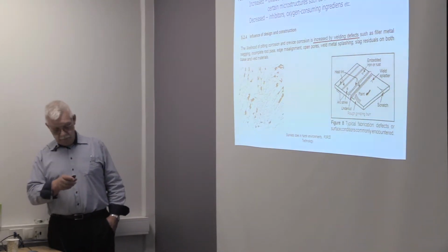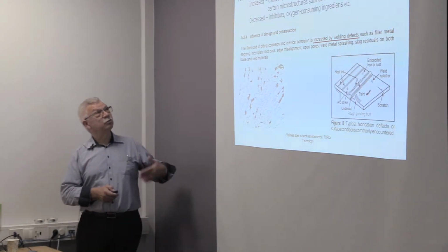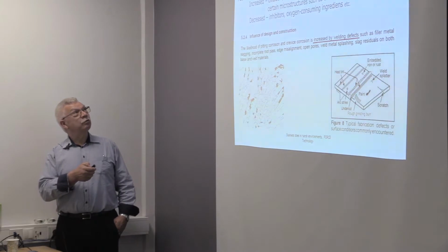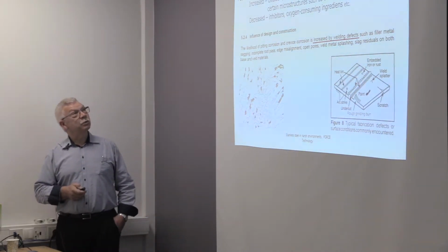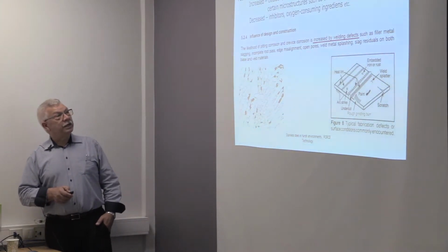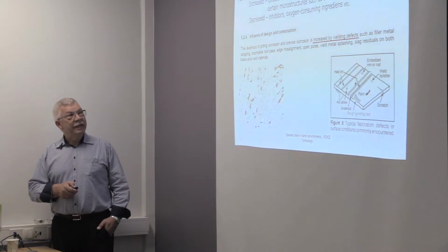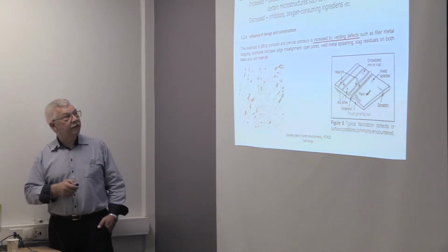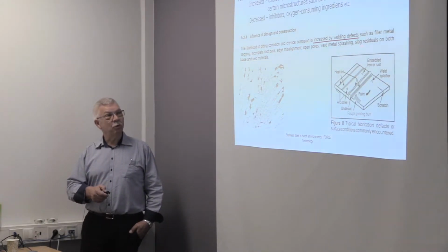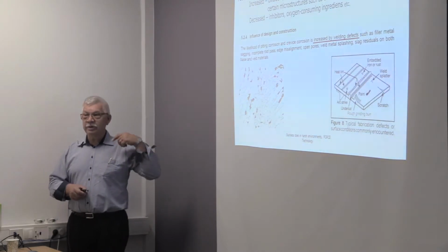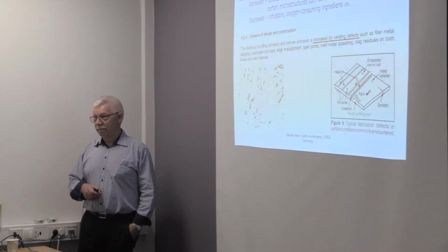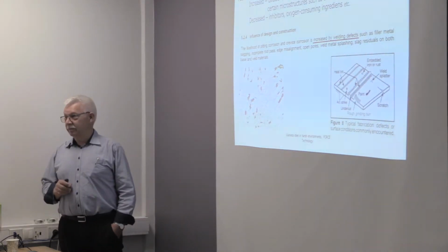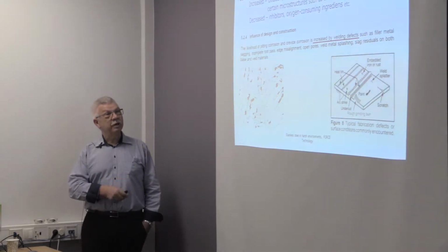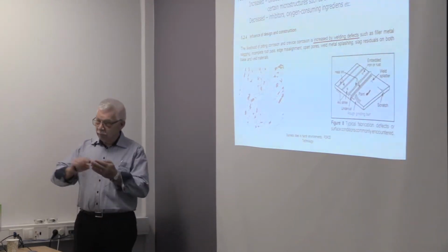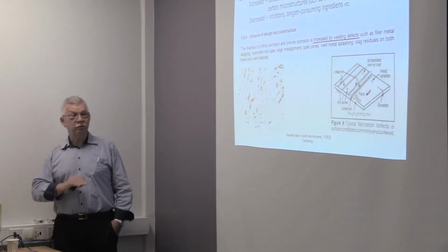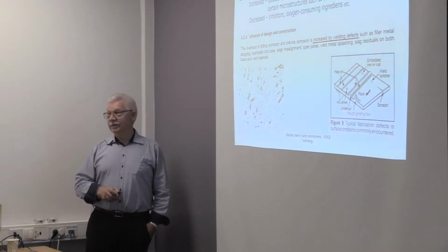We have some help from standards, at least in aqueous, that is water systems. There is a standard called 12502-4, which is an old German standard which has become a European standard. And it says that the likelihood of pitting corrosion and crevice corrosion is increased by welding defects, filler metal sagging, incomplete root pass, edge misalignment, and so on. But this standard is only raising a flag that you might have a problem. You don't have a standard that says you can't have it. It's for the people who are specifying the job to say, oh, we have a standard that says it's not good. We need to write that we don't want it. We want a clean surface. We want no welding defects, or as close as you can get to that, of course.